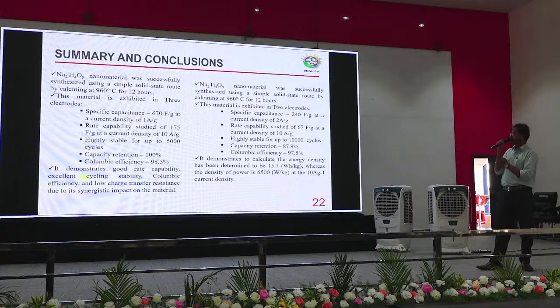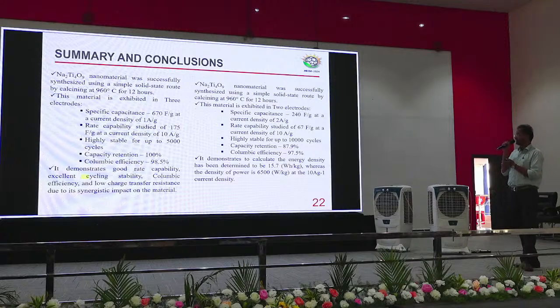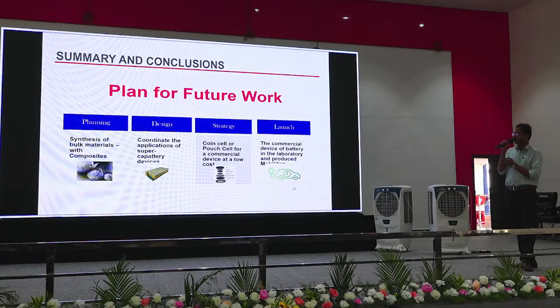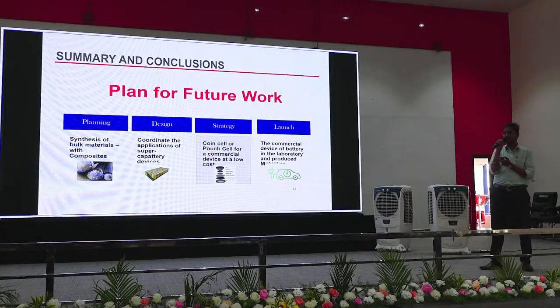Then we move on to the coin cell fabrication of my device studies. In this, the specific capacitance is around 240 farad per gram at a current density of 2 ampere per gram, and rate capability studied at a current density of 10 ampere per gram, with stability around 10,000 cycles, and capacity retention 87.9% and Coulombic efficiency 97.5%. And finally we have calculated the power density and energy density also. And the plan for future work: first, now we have bulk material composites, then move on to design the supercapacitor device and strategy, and move on to devices like e-mobility vehicles.